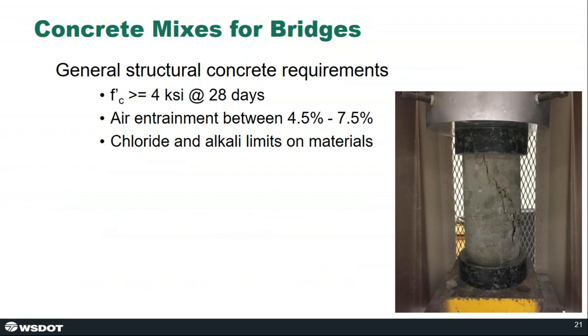So for our general structural concrete for cast-in-place work, we're targeting a 4 KSI compressive strength at 28 days, and we establish an air content between 4.5% to 7.5% to give us some freeze-thaw resistance. Also, we place chloride and alkali limits on the constituent materials, as I mentioned earlier.